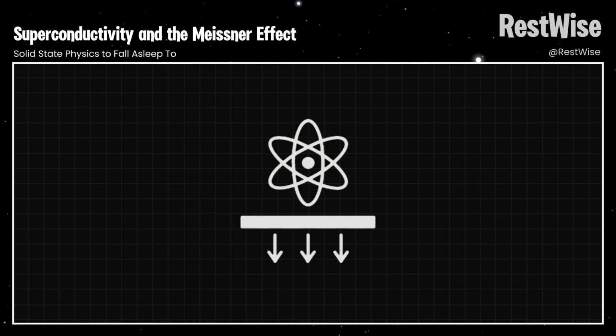Mathematically, this is captured by the London equations, which describe how magnetic fields decay exponentially inside a superconductor. This decay happens over a small length scale called the London penetration depth, typically on the order of hundreds of nanometers. What makes this even more exciting is that the Meissner effect is reversible. If you raise the temperature of the superconductor above its critical point or apply a magnetic field stronger than its critical magnetic field, it reverts to a normal, resistive state and allows magnetic fields to enter again.